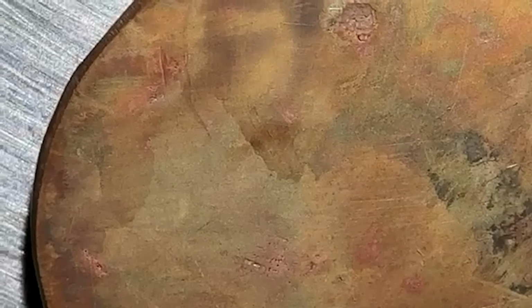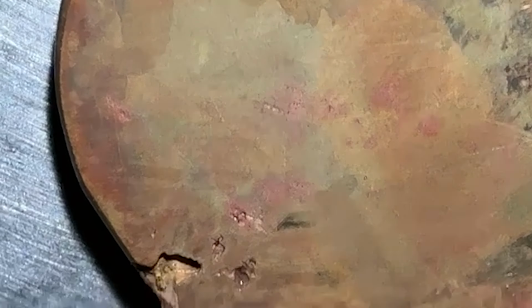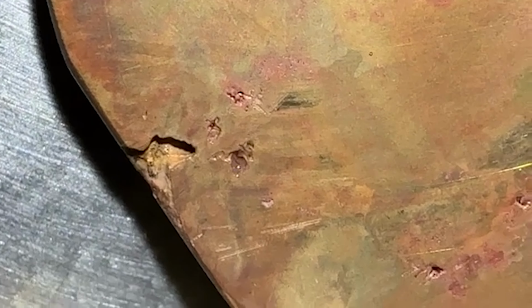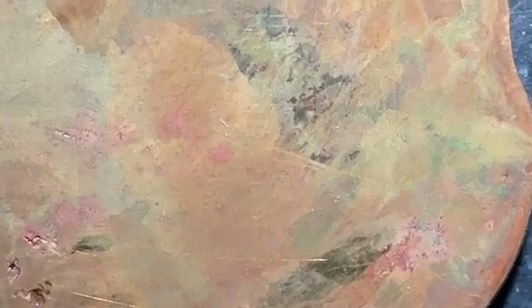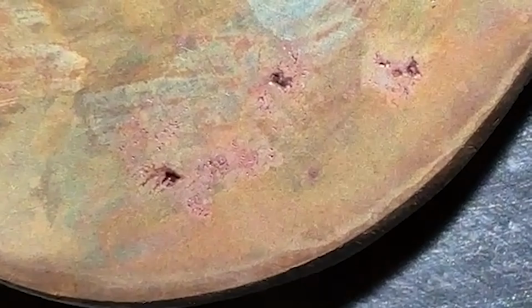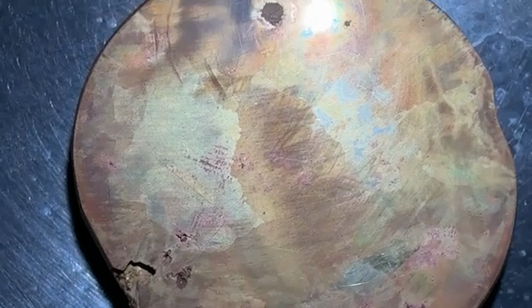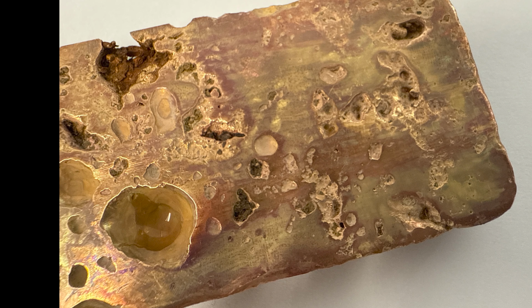I am going to be mean first and tease very slightly, because this is what happened after I polished the disc from the second run. And I think this is really interesting because you can see the grains, but no dendritic brass was formed in the way we were intending, even though, again, we saw really good microsegregation structures. As we get to the end of the video, I think I have an idea about how we can try to prevent this many separate grains from forming.